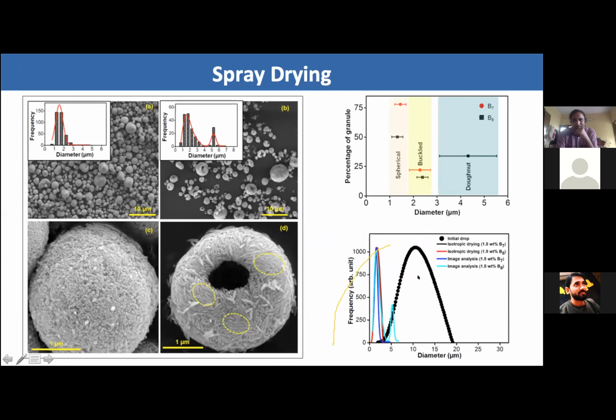And one of our recent contributions in this field is that we have done experiments where we have spray dried droplets with particles of different aspect ratios. On the left side are the images where the droplets contain smaller aspect ratio ellipsoids.